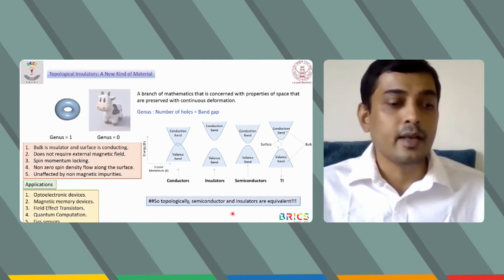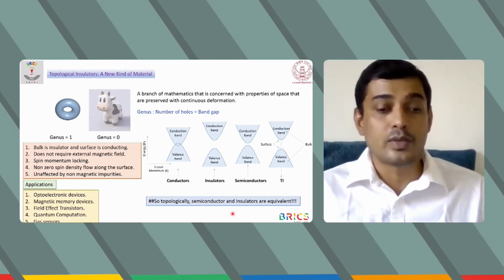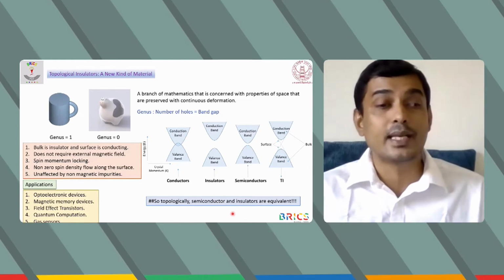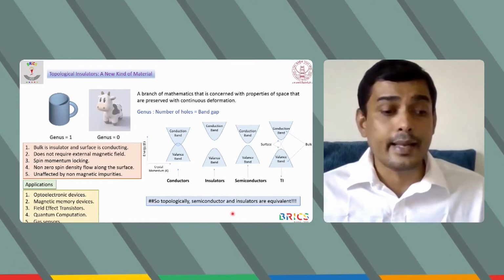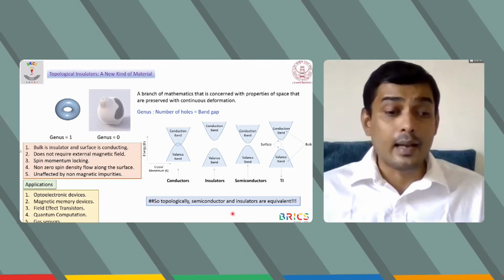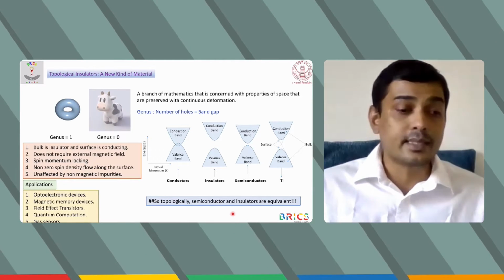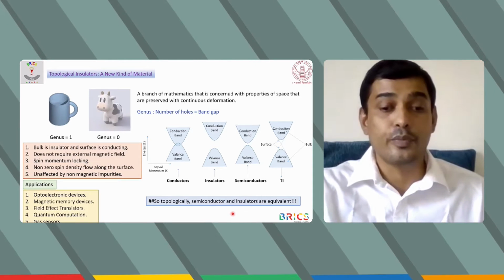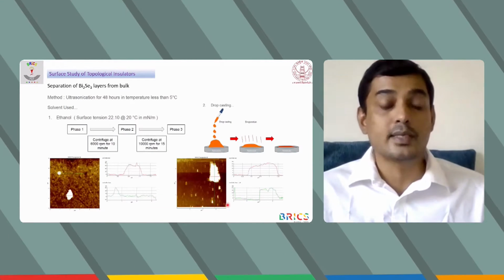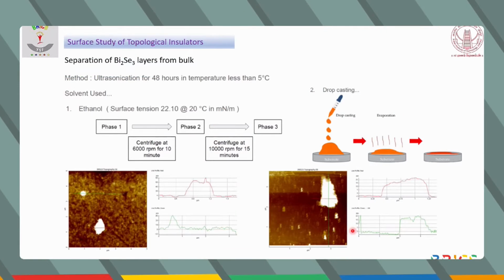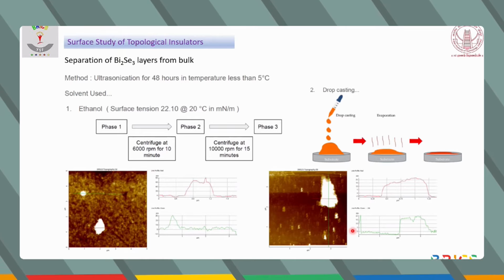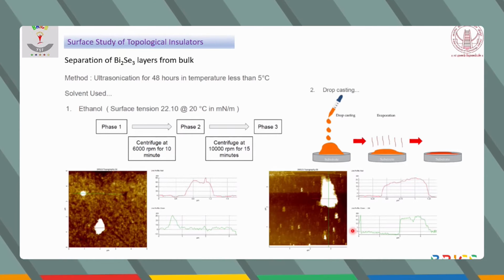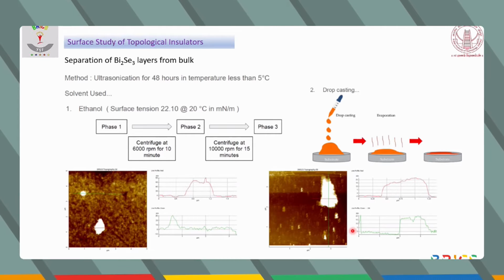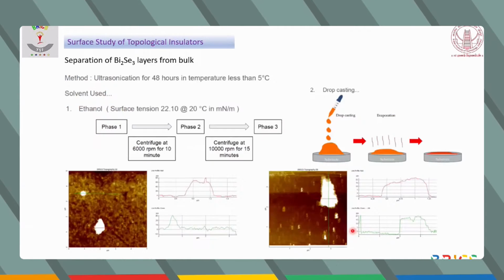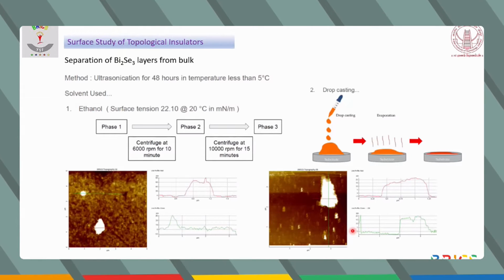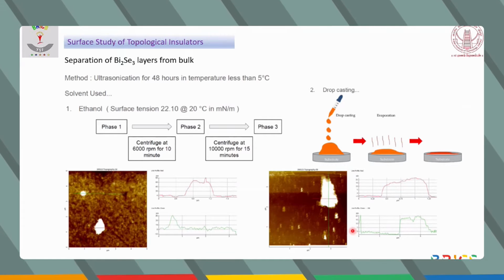that the semiconductor can behave as an insulator, but in terms of electrical behavior, the topological insulators are conductors on the surface and insulator in the bulk. So this property will help studying various devices which were otherwise affected with various problems such as dissipation of heat. So we try to use one such topological material called bismuth selenide, and we try to peel layers of this material by using a sonication method and then drop casting the solution, and we found that these are materials which are isolated from the bulk, and we are now studying these materials in STM for their transport behavior.